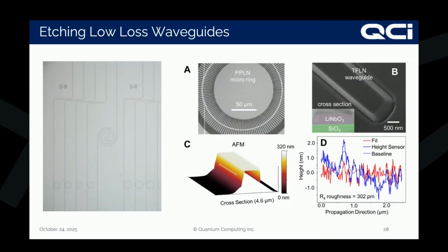We can etch low loss waveguides. We have set a record of reaching sidewall roughnesses of around 300 picometers. It is an important feature because with a roughness as low as 300 picometers, you minimize the light scattering through the waveguide, and through that you can reach waveguide losses as small as 2 to 3 dB per meter. Now, this has been shown before. The goal of the foundry is to reach this result in a repeatable and reliable format. That's a challenge that we have taken on to reach this sort of performance in a reliable and repeatable format, and we are working on it right now.